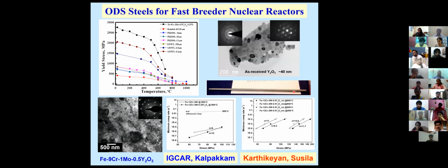Now, this particular steel is useful up to 500 degrees centigrade. The moment you cross 500 degrees centigrade, this steel with 9 chromium and 1 molybdenum will not work. So what we have done is taken nanoparticles of yttrium oxide, embedded them into steel, and we call it oxide dispersion strengthened steel, ODS steel. Now you are putting oxides into it, and these oxides will make the steel very strong, so that even when you go to 700 degrees centigrade, the steel will still be strong. A normal 9 chrome 1 moly steel will not be strong at that temperature.